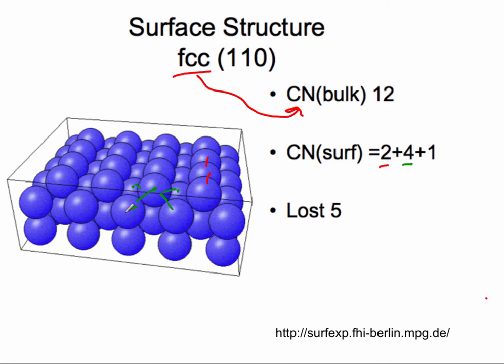If you turn this sideways, you can start to see that each of these atoms is sitting directly above, or is just touching, an atom not in this layer, but even one down from there. You can sort of see that here. You can see that these are touching. So every atom is touching 2 in its row, 4 below it, and then 1 even further below it. So we have a surface coordination number of 7. We started off with 12, so we lost 5.